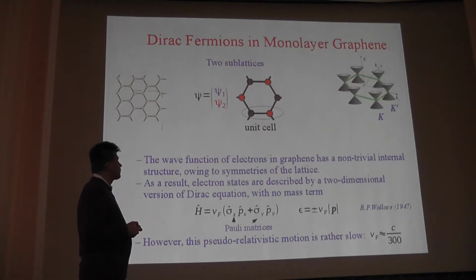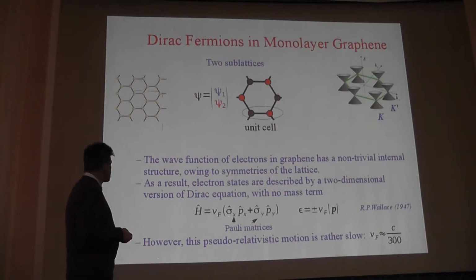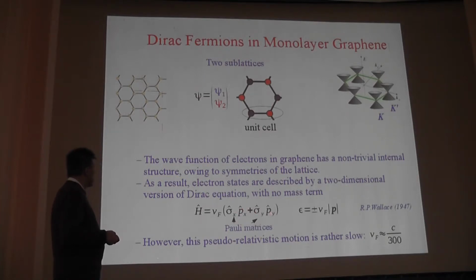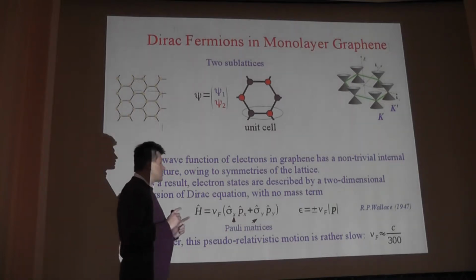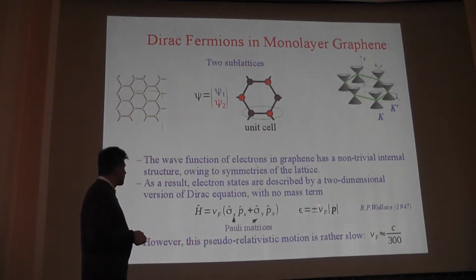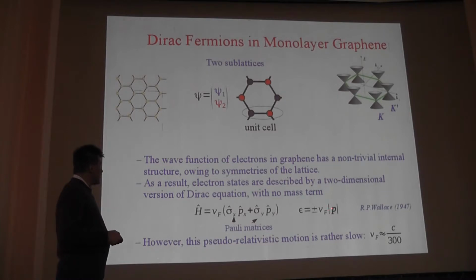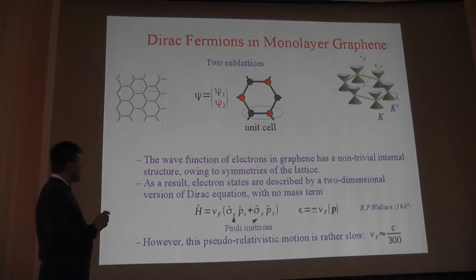A very useful approximation for the electron spectrum near one of these conic points is this Hamiltonian. It's linear in momentum. It has a parameter called Fermi velocity or Dirac velocity. The spectrum of this Hamiltonian is linear, so it can be identified with the velocity of charge carriers. The significance of this equation is that it's very similar to the dispersion equation for relativistic particles, where you have cp. If you try to identify this for relativistic particles, you have to conclude that the effective speed of light is Vf, and the numerical value is about 300 times smaller than the speed of light.